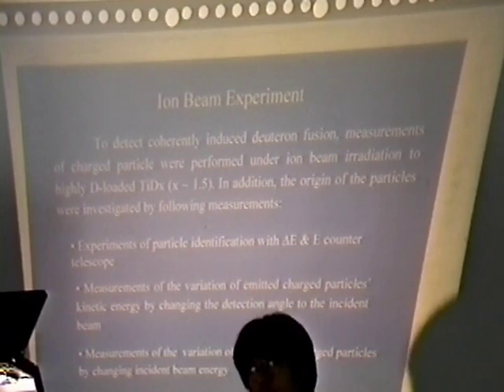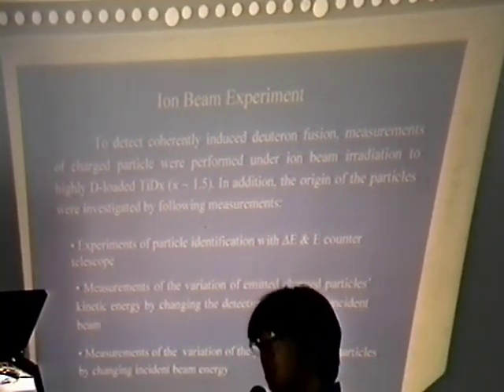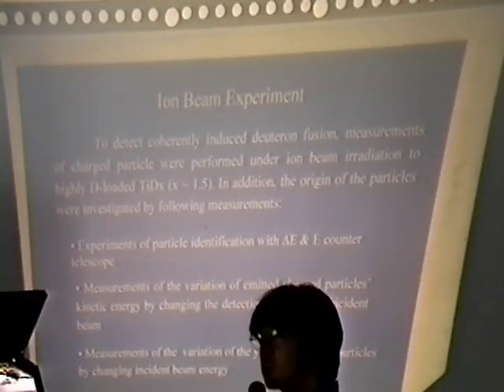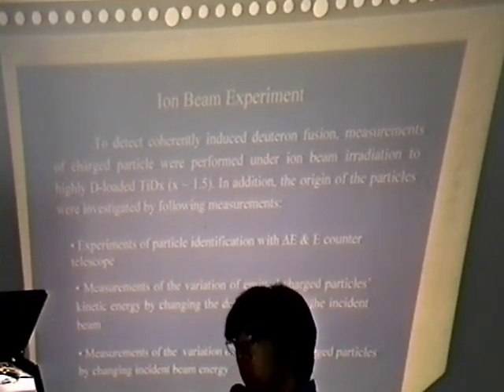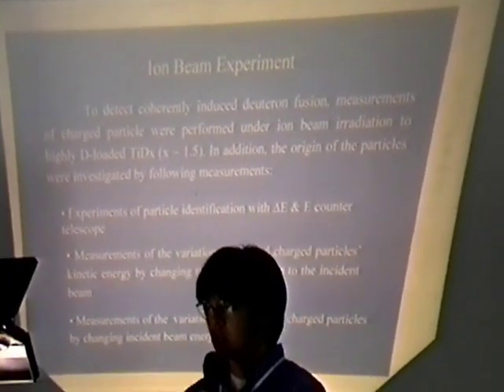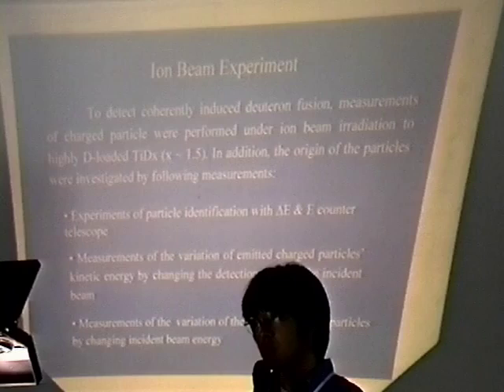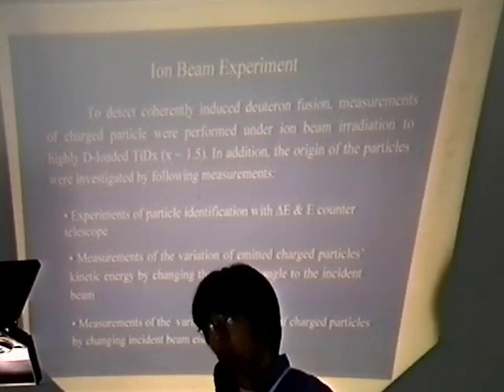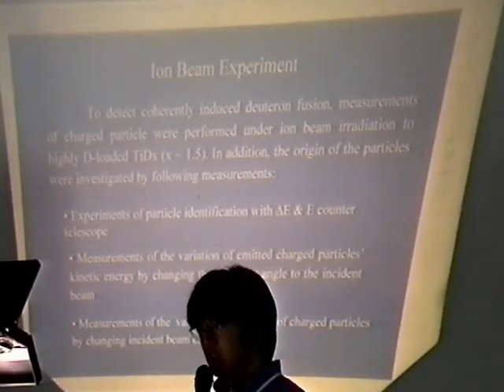Next, I show the ion beam experiment. To detect coherently induced deuteron fusion, measurements of charged particles were performed under ion beam radiation to highly D-loaded TiDx. In addition, the origin of the particles were investigated by following measurements. Experiments of particle identification with delta E and E counter telescope, and measurements of the variation of emitted charged particles kinetic energy by changing the detection angle to the incident beam, and measurement of the variation of the yields of charged particles by changing incident beam energy.